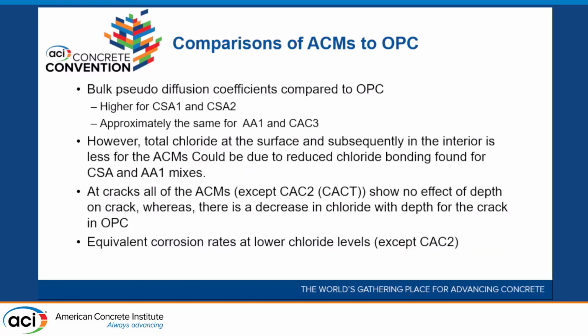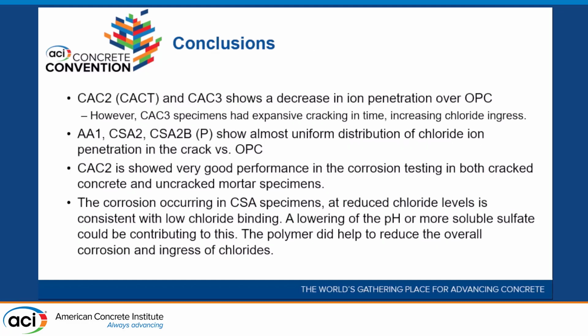So bulk pseudo-diffusion coefficients compared to OPC, higher for CSA1 and CSA2, approximately the same for AA1 and CAC3. Chloride at surfaces and subsequently in the interior is less for the ACMs. It could be due to reduced chloride binding found in the mixes, and all cracks except for CAC2. So except for CAC2, cracks with no effective depth of crack, whereas there was a decrease in chloride depth of crack in OPC. Equivalent corrosion rates at lower chloride levels except for CAC2. And let's see, more decrease in ion penetration over OPC.